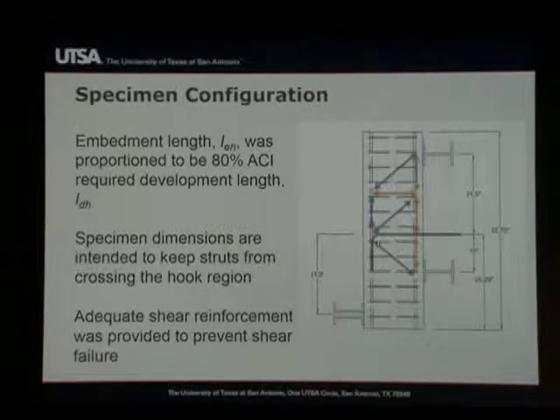And all those arrows in yellow and blue that you see there is a very simple strut and tie model that is illustrating the flow of forces. As we pull on the hook, then we develop compression forces that flow towards the supports. In this case, the support's a little bit far for that strut to make it all the way out there, so it's going to need some help from the transverse reinforcement to find its way up, and then its way again to the support. And so we see in yellow essentially areas where we would expect to have tension in the specimens, and in blue areas where we would expect compression in the members.